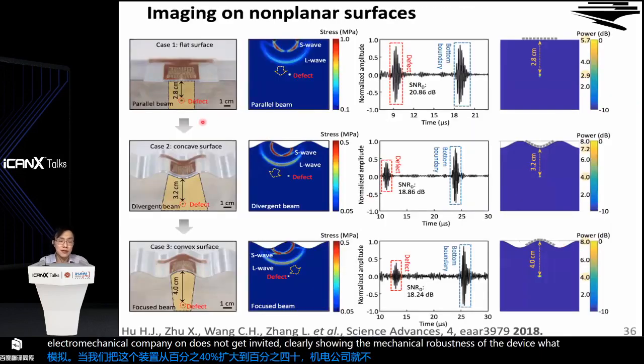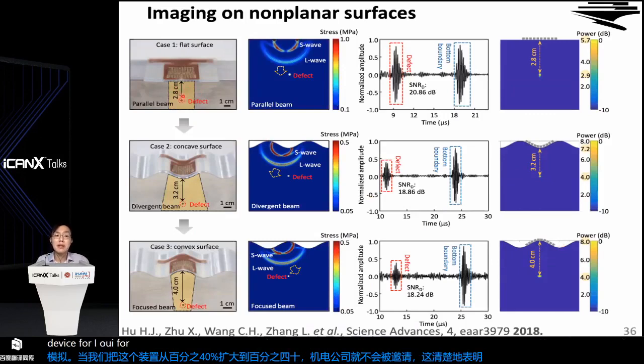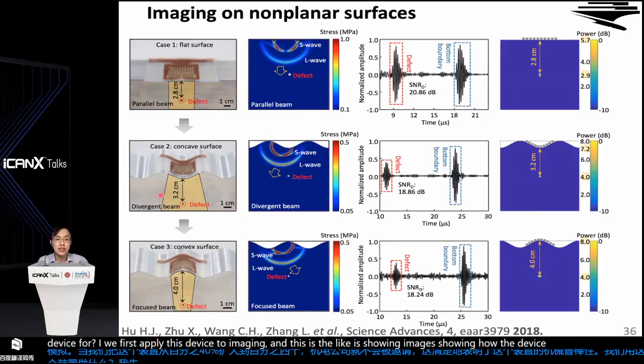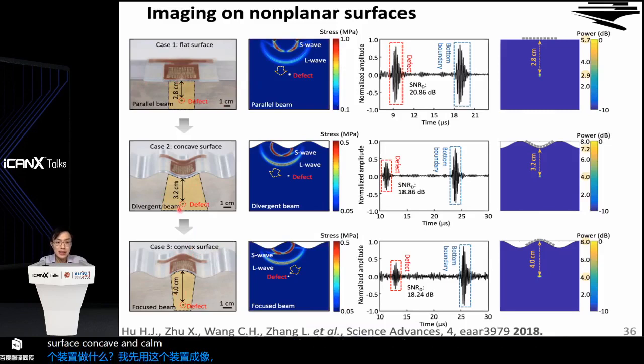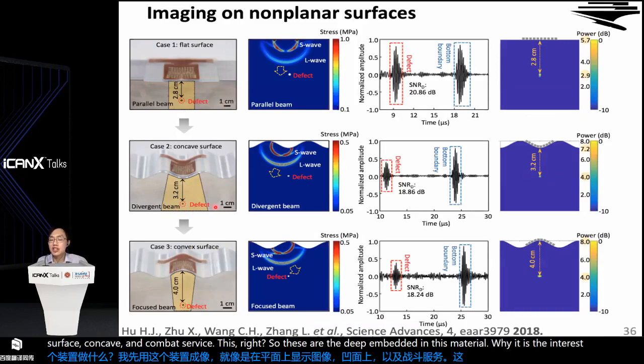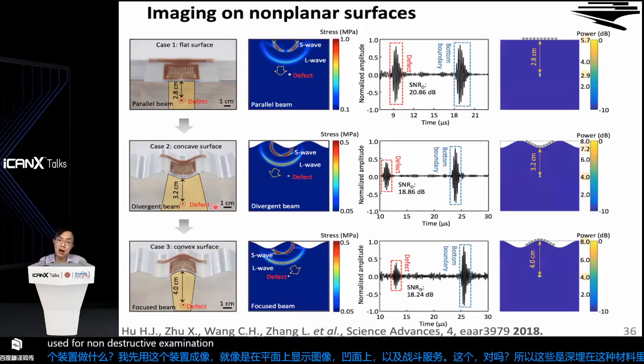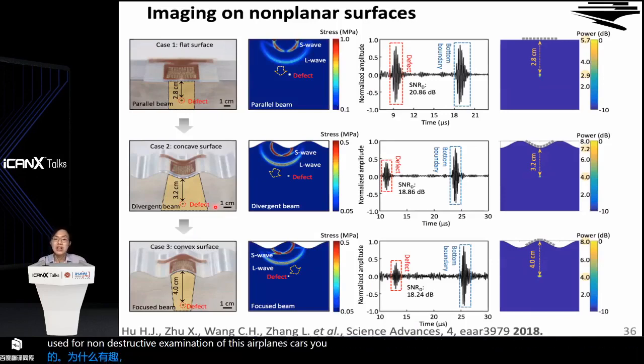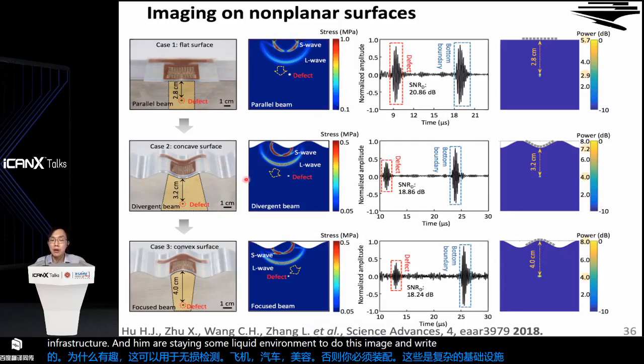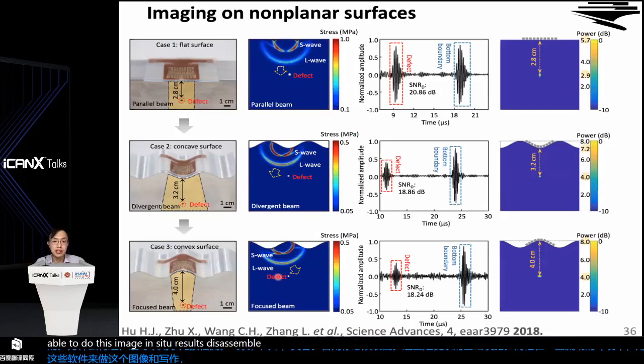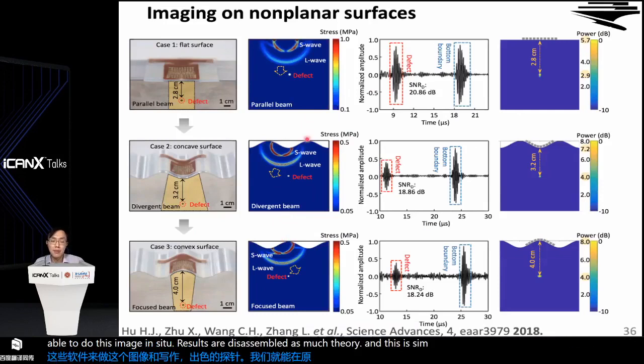What do we use this device for, right? We first apply this device to imaging. And these are images showing how the device images on a flat surface, concave and convex surfaces, right? So this is the defect embedded in this material. Why is this interesting? This can be used for non-destructive examination of airplanes, cars, buildings, bridges, right? Otherwise, you will have to disassemble those complex infrastructures and immerse them in some liquid environment to do this imaging, right? So with this soft ultrasonic probe, we will be able to do this imaging in situ without disassembling this material.